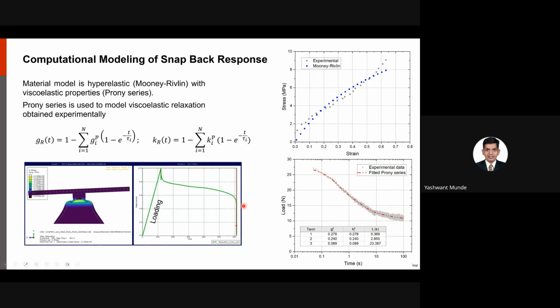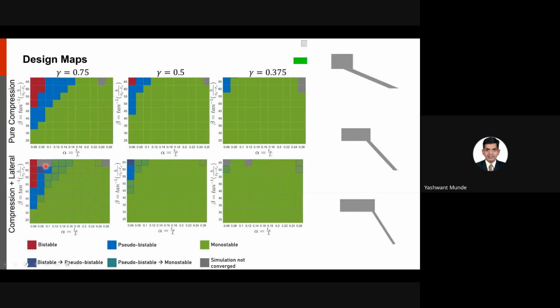So with these simulations, we developed process maps or design maps, where basically we have alpha, which is the thickness in the x-axis, the slope in the y-axis, and each of the columns is corresponding to different curvatures, that is decreasing curvature from left to right. And the first row is for just pure compression case, and the second row is a combination of compression and lateral loading. So we have three examples here. I've just chosen 3 random cases. As you can see, the top one immediately comes back to its original state upon releasing the load. The third one is still stuck in its second stable state. It's not come back. Whereas if you notice, the second one has a time-delayed snapback. So this is pseudo-bistable, monostable, and bistable.